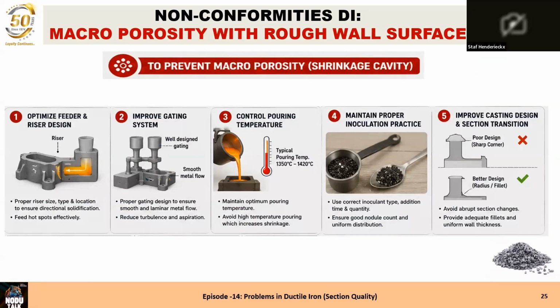The gating system is another one that has an influence. Why? The gating system will decide where the hot spots will be, besides the section differences. Very close to a gate, there will be a high temperature, and it's very important to improve the gating system so that the riser can feed it when it's necessary.